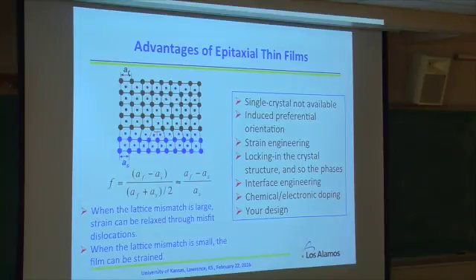Quickly, for students' purpose, what's really the advantage of epitaxy? Here, you have this substrate, and then you have the thin film. It's not in scale, of course. And due to the lattice mismatch, you can really grow the material. If that's relaxed, you form the defect. If not, the strain. So basically, that's the very simple way you look at things. You look at the lattice parameter of the film and the substrate, then look at this mismatch, and then you can think about whether it is really epitaxy or not. You can do it or not.